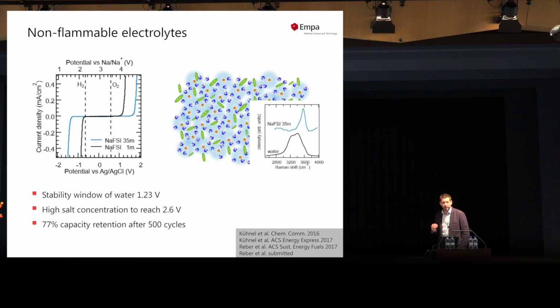So when you are reaching these very high salt concentrations, basically there's almost no free water left, and all the water molecules become part of the first solvation shell of the cations. You can see this here in the signature of Raman. I don't have time to explain this in more detail, but there's a clear structure change in how the water behaves. This allows us to improve the electrochemical stability window quite significantly. So we reach a stability window of about 2.6 volt. That's not yet 3.7 volts like in a lithium-ion battery, but still an improvement.